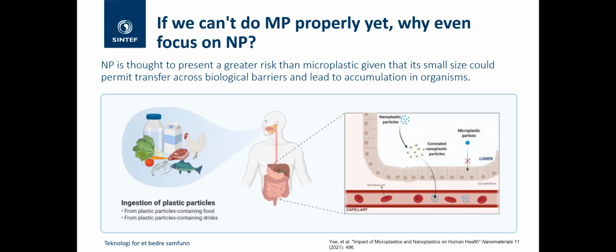It's interesting because we think that nanoscale particles are likely to be a greater risk than micron scale particles. There's a lot of work that's been done on nanomaterials in the last 20 years from an environmental and human health perspective. We know that there are risks associated with particles at that scale. The reason why microplastic is thought to be maybe less of a risk is that those particles are, in theory, too large to cross most biological barriers. If you ingest it and it's going through the body, the gut is not going to allow large micron-sized particles to pass through and lead to accumulation. But we do know that nanoscale particles can pass through biological barriers. It's a bit of a grey area right now in terms of exactly where this cutoff is and what size particles can transfer and accumulate in the body. That's one focus of research at the moment.